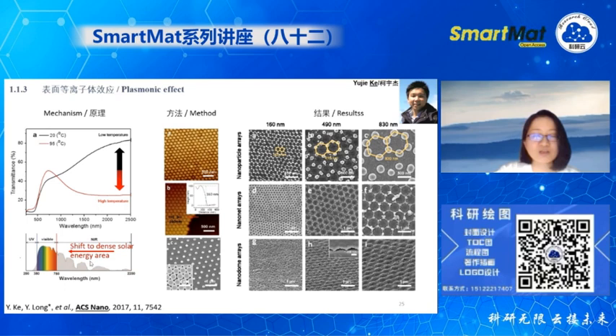So first of all, why do we need to study plasmonic effects? Because this is solar energy density. You can see solar energy density has different density at different wavelengths. So obviously, if you want a very large solar modulation, you prefer your large modulation to occur at this higher density solar energy area. Am I correct? Okay, so this is the justification why we need to study this plasmonic LSPR. We call it the plasmonic effect of this tunable vanadium dioxide.